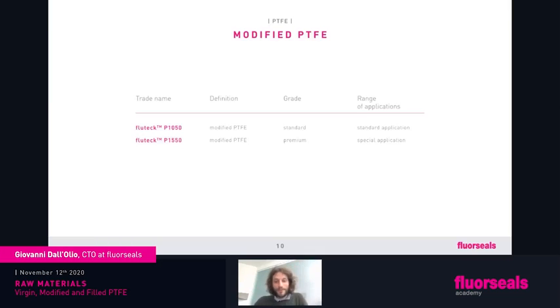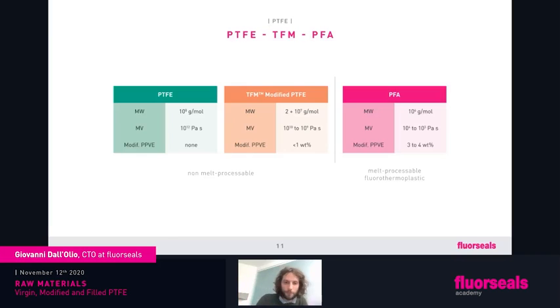How do we trade modified PTFE? It's quite easy. It's a fluteck P, because we mentioned it, that's PTFE: 1050 and 1550. 1050 is the standard grade. Again, virgin PTFE is P1000. Modified is P1050. So the 50 states the modified resin at the base of the material. That's also for our compounds, we will see. And 1550, it's again 15, premium grade, 50 modified PTFE.